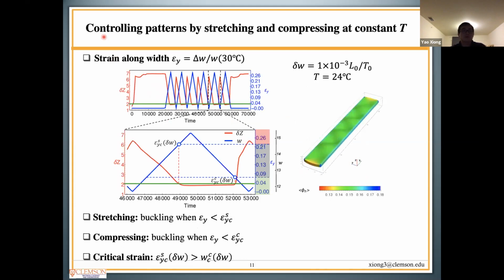Here, we periodically stretch and compress the gel along the width at 24 degrees Celsius. The blue line here is the strain profile, and the red line is the amplitude. Before introducing cycles, we quench down the temperature of the gel from 30 to 24, and the confined gel takes enough time to achieve the fully developed pattern. If the amplitude is above the green line here, it means that the gel is buckled. During stretching, the sample remains buckled until the strain reaches a critical value, and the gel maintains the flat configuration to a lower critical strain during compressing.